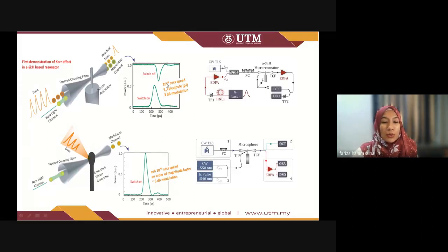So now, instead of requiring hundreds of watts of peak power to observe nonlinear interactions for signal processing, we need less than a picojoule of energy to observe all these switch-on and switch-off conditions at picosecond time regime, and